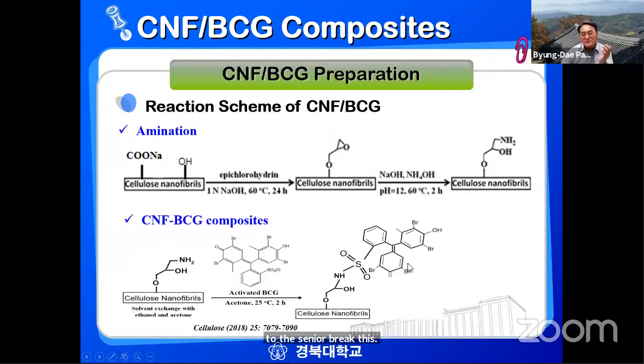And then we also tried amination. It's the same nanocellulose fibrils, and then we use epichlorohydrin and make some reactions, and then provide the amino groups on the surface. And then we make a reaction of the aminated CNF with activated BCG to make this kind of conjugated product.